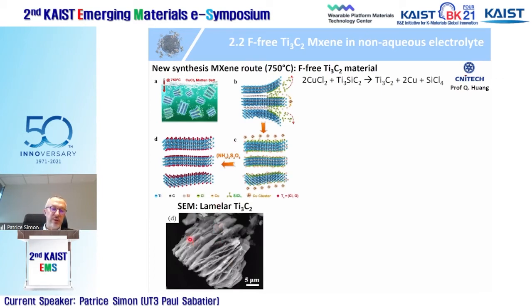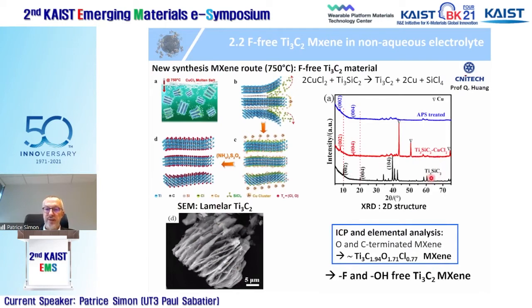And after washing, what you can see is very nice laminar Ti3C2. The XRD patterns tell you that yes, you move from the MAX phase to the 002, 004 00L layers of MXene. There is no silicon, with, I would say, copper onto it. And here, after washing with APS, there is no more copper, and you end up only with 00L peaks of the MXene. And ICP and elemental analysis confirm that we prepared oxygen and chlorine (Cl) terminated MXene.